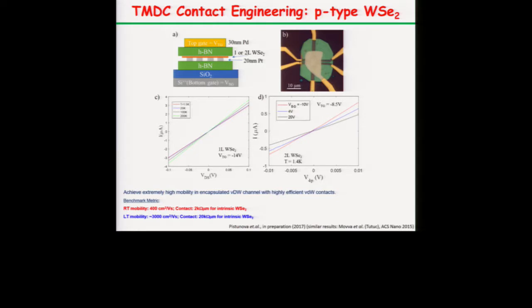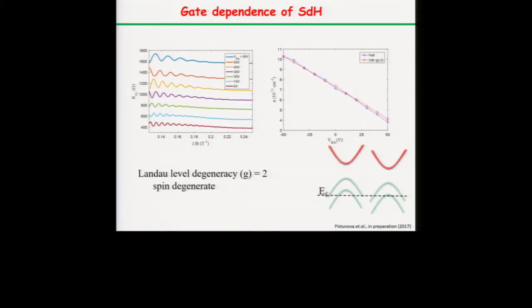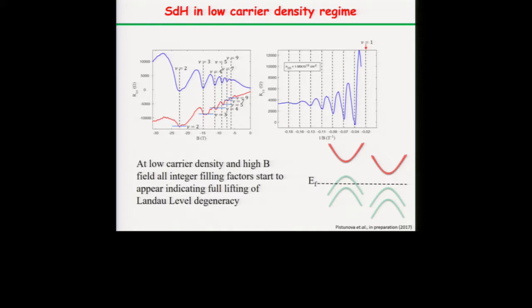With this, we've been able to obtain gate dependence of Shubnikov-de Haas oscillations. That's the first thing. We apply a magnetic field, and then we form Landau levels, right? And then we can see these Shubnikov-de Haas oscillations. We find this at large doping. We can see a spin degeneracy of 2, because we have a spin up and a spin down, but at different values. And if we go to even lower carrier density, we can see that instead of forming a g equal 2, now we have a g equal 1. So we have lifted the Landau level degeneracy, because we are only probing one of the valleys in that case. But in Landau levels, right? We can go to very low carrier density, to around 1 times 10 to the 12.